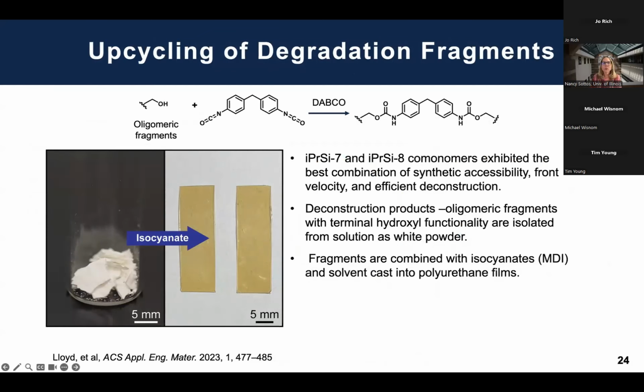So basically, once we deconstruct this material, we're left with the oligomeric fragments. And one of the first things that we did is, well, what can we make of them? At this point, they can't go back to dicyclopentadiene. And what we added was a catalyst. And the idea is that by adding isocyanate and catalyst, we can bring this system back to another useful polymer. In this case, we've made it into polyurethane. And it actually makes a really nice polyurethane film.